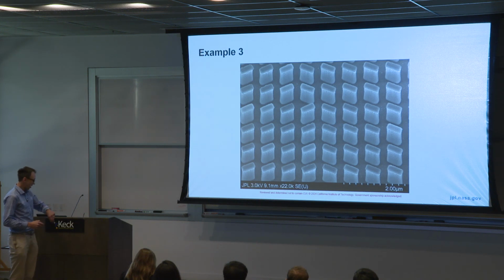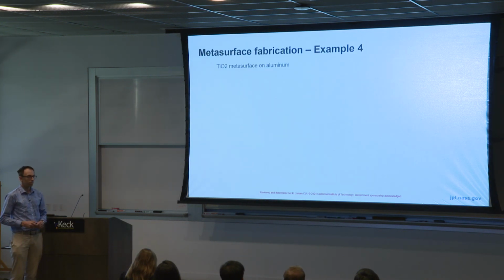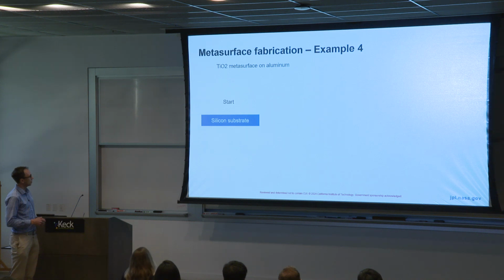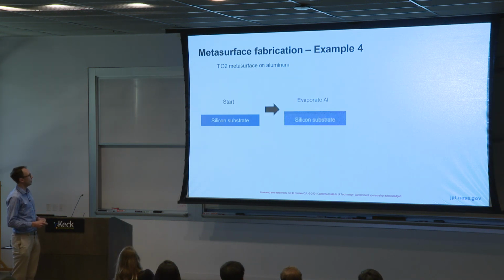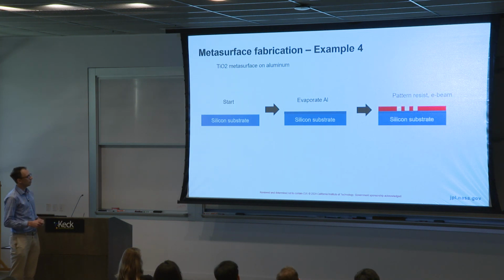Okay, so my fourth and final example is going to be using a titanium oxide metasurface on top of aluminum. So this is going to be a reflective metasurface. So you would start with a silicon substrate. So notice how the word silicon doesn't really appear here, but if you can, you work with silicon. And I'll return to that point. So you deposit aluminum onto which you pattern a resist. So you make little holes to define your metasurface.